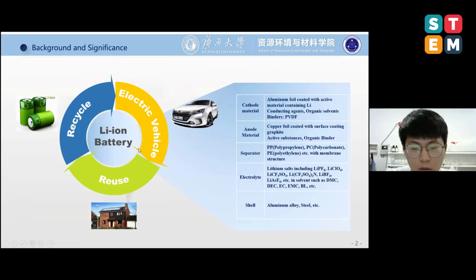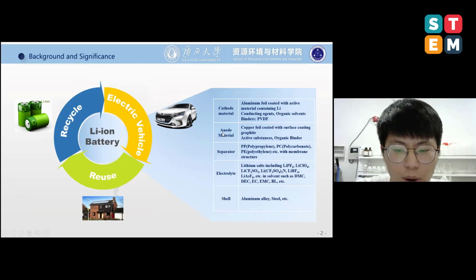What is the composition of lithium-ion batteries? It always has five parts: cathode materials, anode materials, separator, electrolyte, and outside shell. The cathode materials are aluminum foil coated with active material containing lithium, conducting agents, organic solvents, and PVDF binder. Anode materials are copper foil coated with graphite, active substance, and organic binder. The separator is PP or PE, and so on, with a membrane structure.